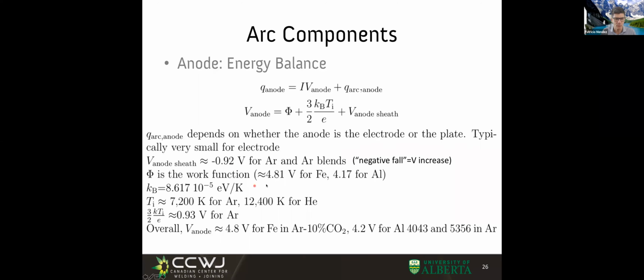And I put some numbers here, which you do not need to memorize. But the one number that really matters is that this voltage of the anode overall is more or less 4.8 volts for iron in argon 10% CO2, or 4.2 volts for aluminum. We measure them. I know if you put these voltages, you get wire deposition rate quite well, right? And what is here is trying to explain where this voltage comes from, and why this voltage is so close to the work function.